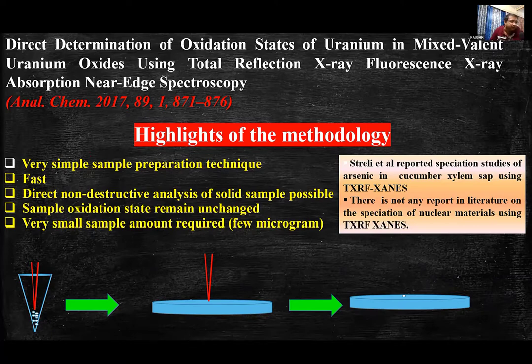During the TXRF-XANES sample preparation, we take a few microgram of the sample and touch it with a tip. Then we touch this tip on the center of the quartz sample support. So a few microgram or few nanogram of sample will be stuck on the center of the sample support, and that is sufficient to give good counting statistics, so we can do the TXRF-XANES measurement. You can see that there is almost negligible sample preparation involved.